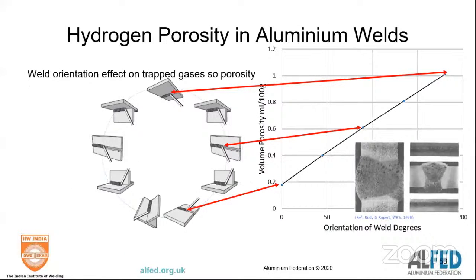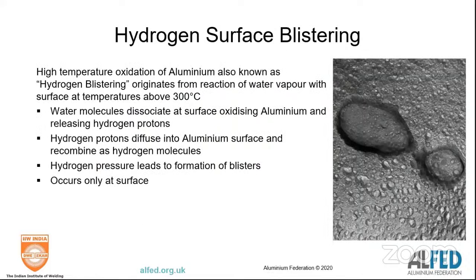So when you're TIG welding, the position of your weld is important. If you're welding upside down, hydrogen, being a low weight gas, will float up and you'll increase porosity. So when you're designing your welds, be aware of hydrogen and be aware of the porosity. One of the problems with hydrogen is if you've got damp atmospheres or high humidity, water will decompose through a chemical reaction on the surface of aluminium and will form bubbles on the surface of aluminium.